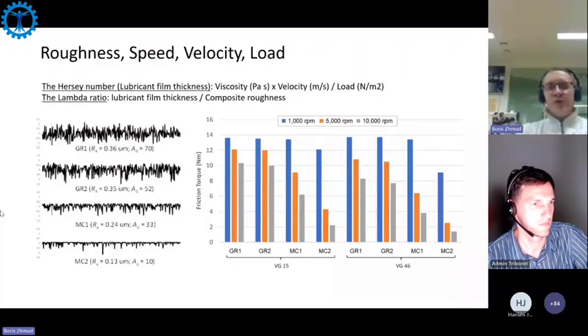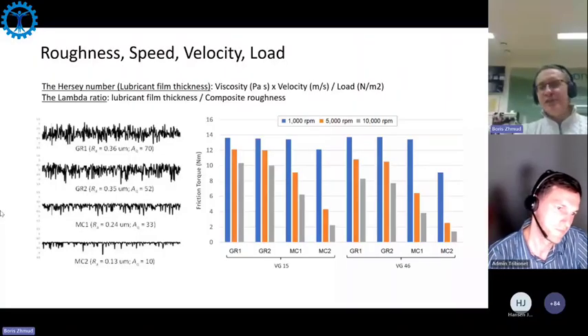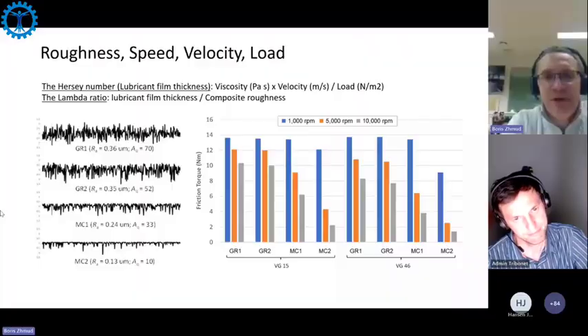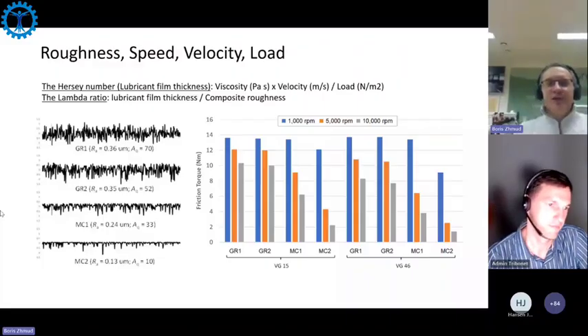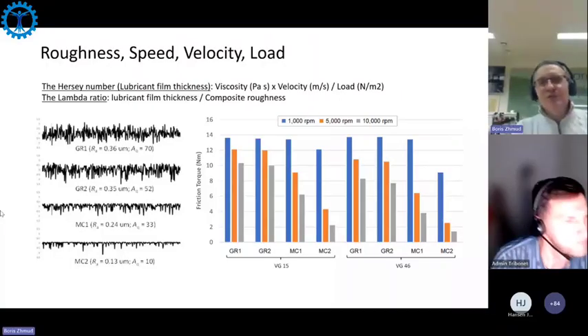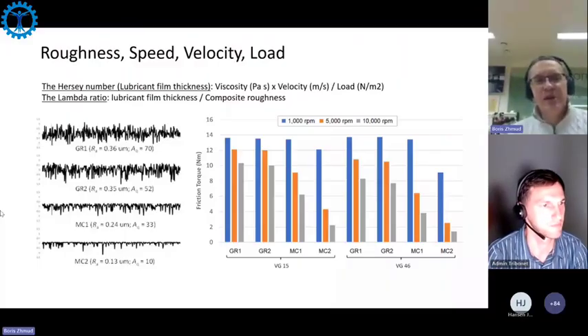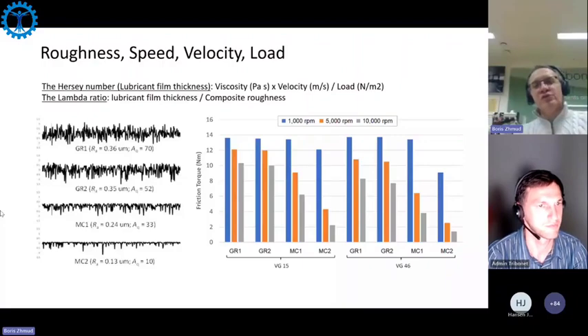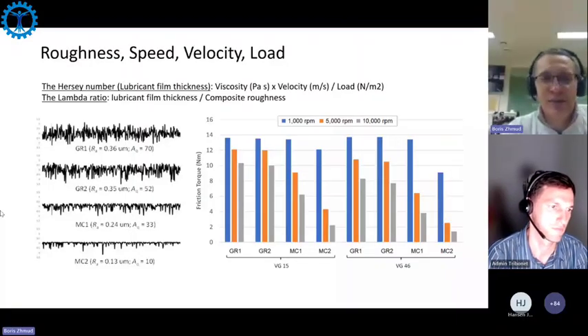So it's interesting to look at the effect of roughness, speed, velocity, and load. And this is very simple. This is where basic tribology comes through. You talk about the Hersey number, which is the product of velocity multiplied by viscosity divided by load, and is a representation of film thickness. If you go to higher velocity, you can reduce viscosity, because you still will have sufficient film thickness. And you talk about the lambda ratio, which is the ratio between lubricant film thickness and composite roughness. When you go to a smoother surface, you can work with a thinner lubricant film. So this is a very easy explanation of why mechano-chemically treated surfaces shine: they work very well at high speed operation, but they also prevent scuffing in low speed, high load operation. That was supported by simulation, and it was also supported by a real test.